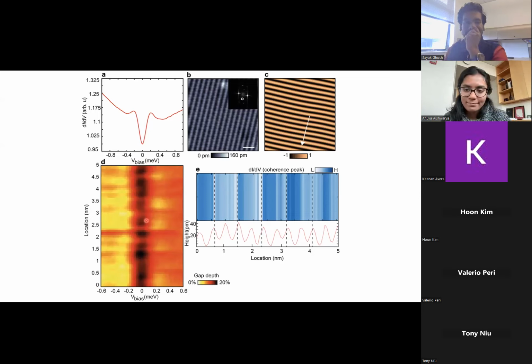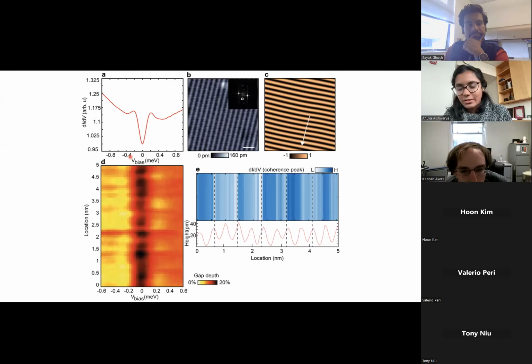It becomes like a resolution issue, I guess, eventually. Yes. So maybe if someone has a dilution fridge with an STM, they can try to do it. And I'm not sure that it's going to help, because one of my old lab mates in China had an 80 millikelvin fridge, and got their hands on UTe2 somehow, but their gap also looked identical. So this is probably not a resolution issue. The reason the gap is shallow is probably something to do with UTe2 itself. But they never tried doing a vortex lattice.